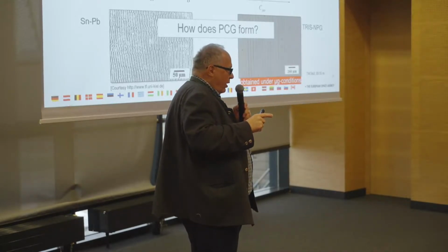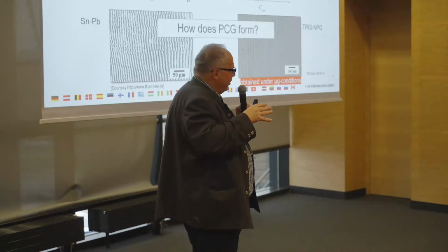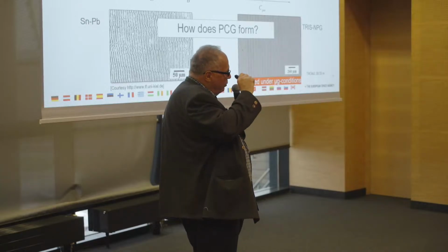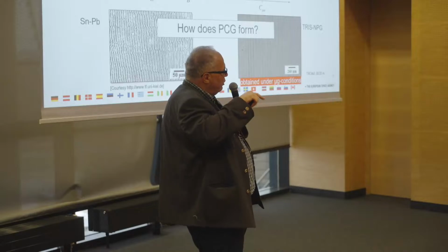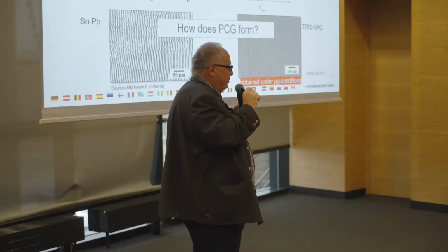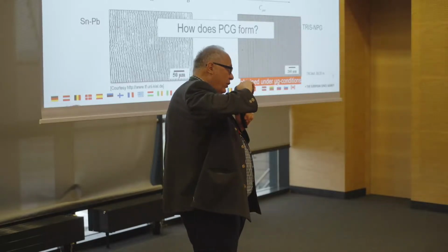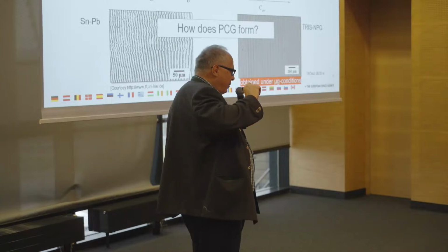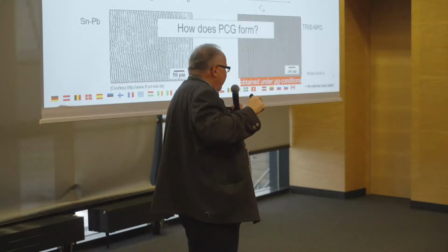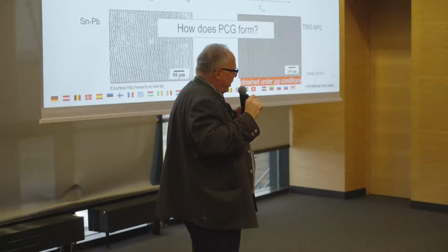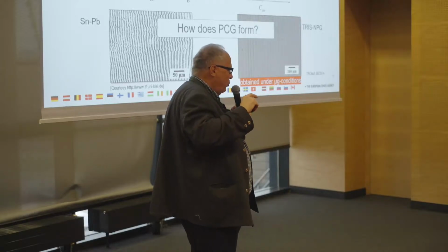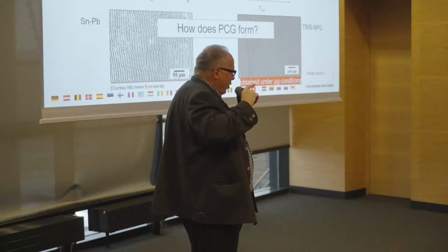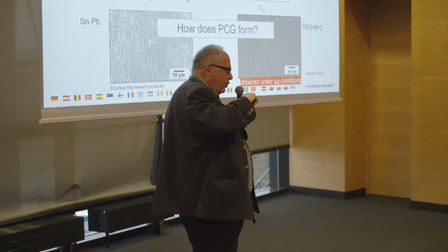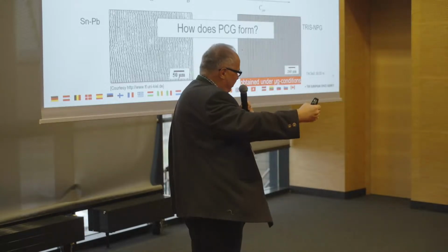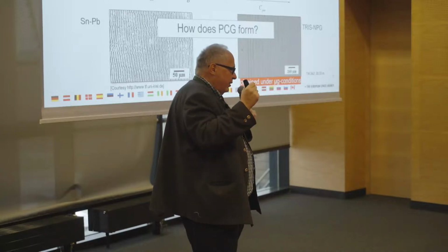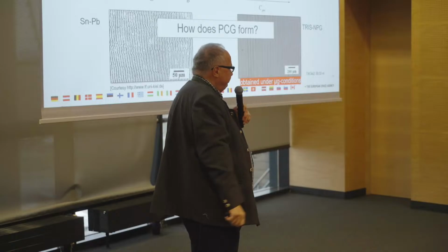On the other hand, we tried to reduce the inclination, and the consequence was that we get only a small black line where we have a lot of problems now to interpret the patches. We found exactly for these experiments where we wanted to reduce the incline, patches and rods. So if we get the opportunity to make space experiments again, I believe one part will be to increase the incline. I know this makes a problem concerning the concentration difference between the front and the back. But nonetheless, it makes it much easier to understand how they formed. So it's an advantage in this.